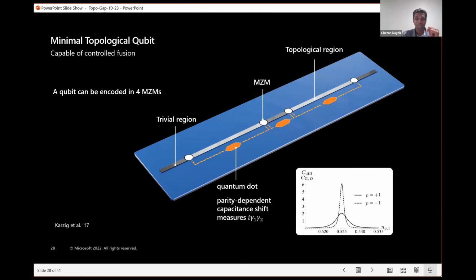That capacitance shift depends on the parity shared by the Majorana zero modes. It's effectively an interference process along a loop like this. So for one parity, the capacitance looks like this as a function of gate voltage, and for the other parity it looks like this. So the shift in capacitance caused by the coupling of Majorana zero modes can be quite different for the two total parities. That's what ultimately you would measure in order to measure the fermion parity shift, or equally well to measure this qubit in the Z state, do a Z measurement.